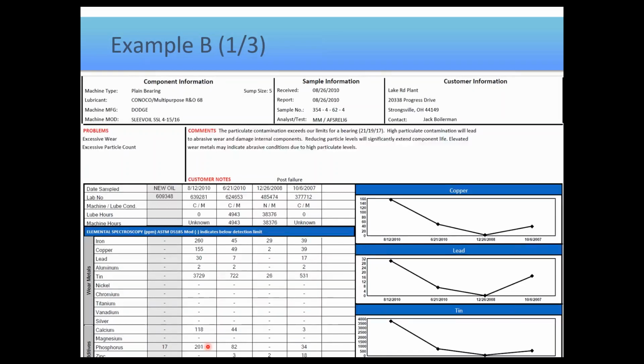So that could be possible. If you told me that you had both an R&O 68 and an EP 68 on hand in your lube room, we might consider that somebody just grabbed the wrong one and grabbed the EP instead of the R&O. Now either solution, the grease ingression or the wrong oil, could explain why we have so much wear particulate. But the wrong oil, being that we just put EP 68 in there, doesn't explain why the particle count went up and the dust and dirt up here, not at least entirely.